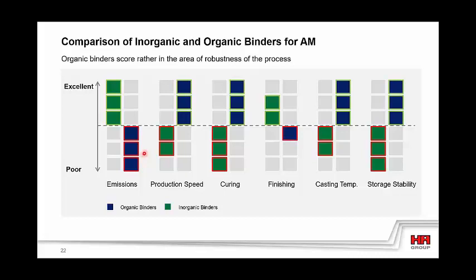Going to the production speed, furan's key benefit is the speed of the printing process. The favorable viscosity and reactivity of the system, as well as the optimal drop formation at surrounding temperature, have a positive influence on this aspect. In the inorganic process, tempering of the surface layer is necessary to stimulate reactivity when using silicate binders. Recoating in this case takes place at a slower rate than in the furan process, which partly explains the slower printing speed.